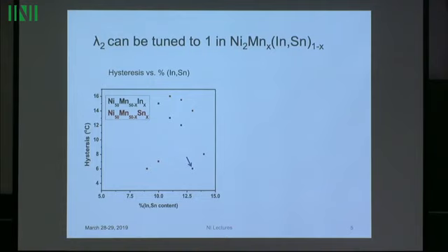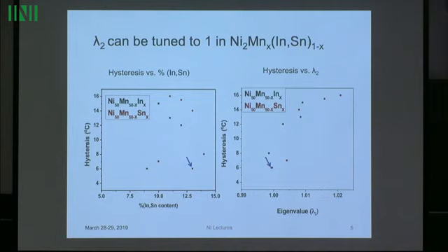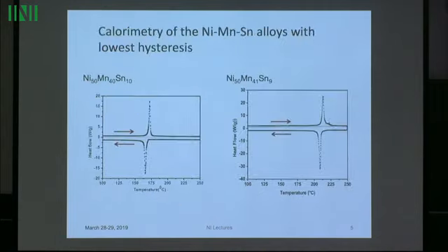I don't have the latest graph here. It's even gone down to 3 or 4 degrees, which is typically the best we can do, or maybe 2 degrees in some bulk materials. And so those are the nice calorimetry graphs showing heat flow versus temperature, as I already described, showing the peaks due to the latent heat of phase transformation. Heating and cooling, and you can see the small hysteresis.